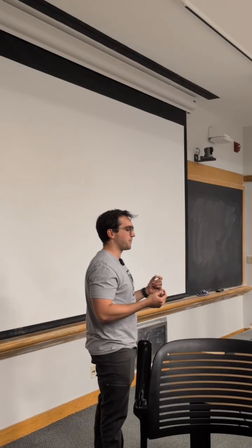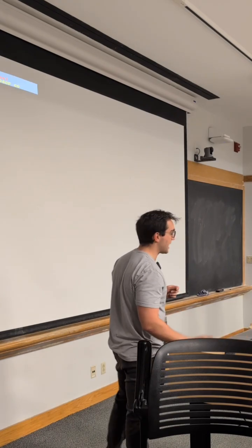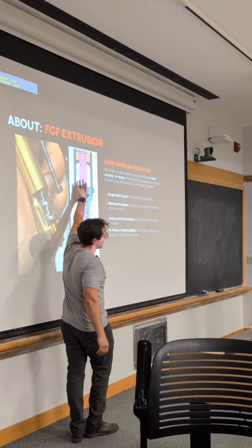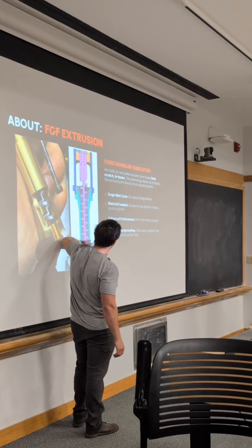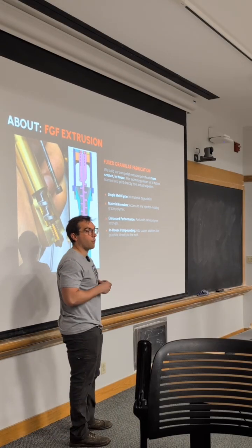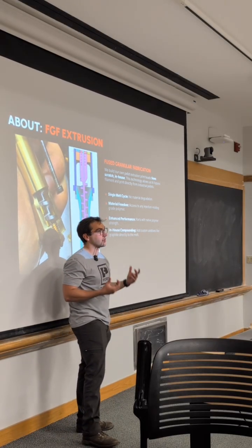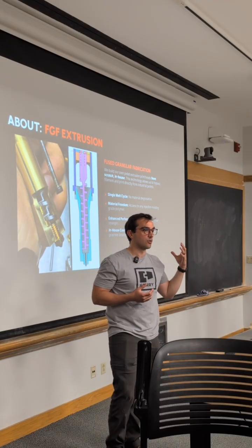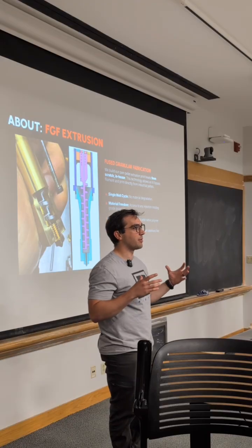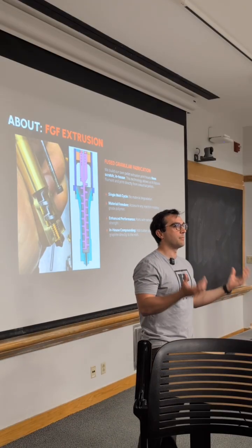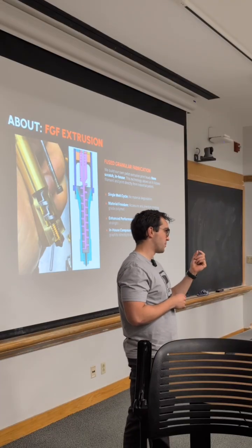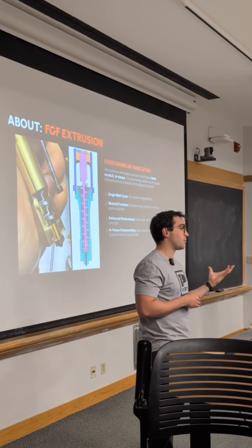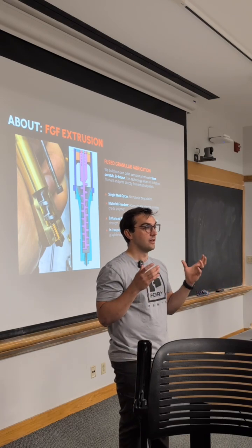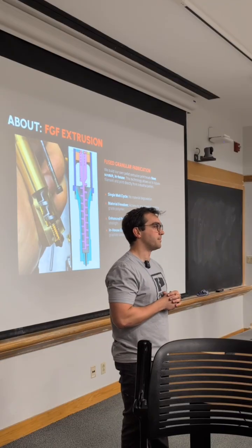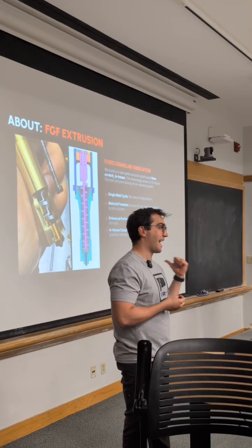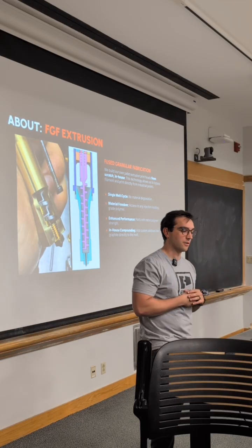And the important part with that is if you go back to the design of the print head, you can imagine that, call it ambient temperature here, and we're getting progressively hotter throughout. Eventually, at some point, that water inside the pellets is going to flash boil. And that's going to create significant variations in your ability to control flow. So if we can pull all that humidity out of the polymer entirely, then we get much more reliable and repeatable results. When the water flash boils inside the barrel, it causes a pretty dramatic variation in part cosmetics and part strength, and we've made a lot of bad parts because of that specific issue. So fixing it was really critical.